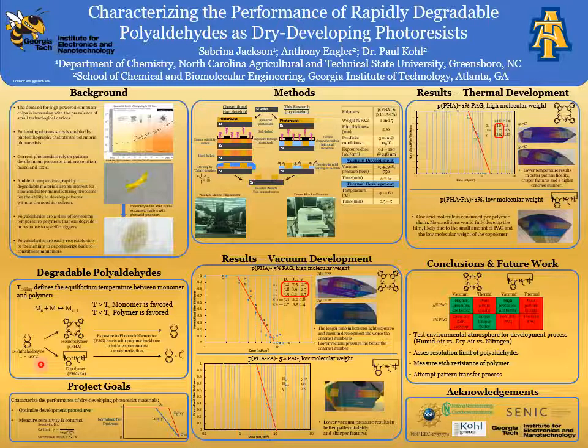The way we characterize a photoresist is by doing a contrast curve. The D0 value is when the photoresist starts to develop, and the D100 value is when the photoresist is completely developed. The contrast value can be found by using the formula 1 over log base 10 of D100 over D0. We are comparing our photoresist to the commercial target contrast value between 2 and 5. The contrast values are created using a contrast mask that lets different doses of light be produced onto the substrate.